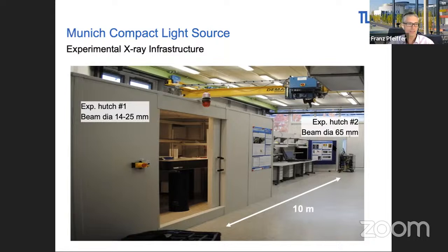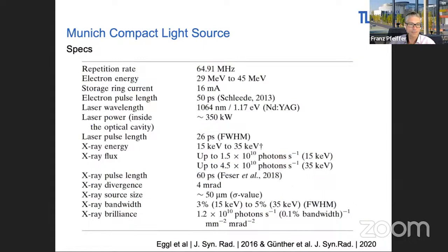So presently we have 2 hutches, one where we use beam sizes of about 14 to 25 millimeters round in the first hutch, and one further downstream where we can let the beam travel and then expand to its natural width of about 65 millimeters, pretty much in a round shape. And when you have a facility, of course, you need to plan that you have enough space for these experiments. Here are some overview parameters.